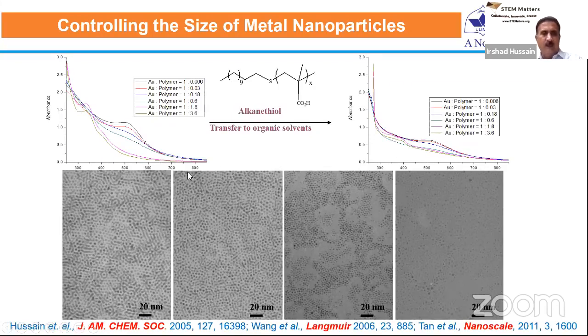If you carefully look at the absorption spectrum of these nanoparticles, initially they have a surface plasmon resonance band when they are bigger than 2 nanometer. But if the particle size is smaller than 2 nanometer, there is no more surface plasmon resonance band. That means that they are no longer acting as metals.